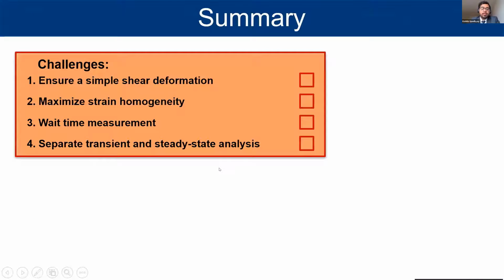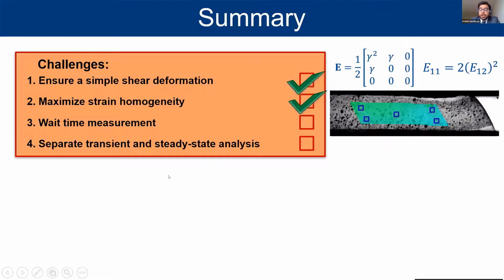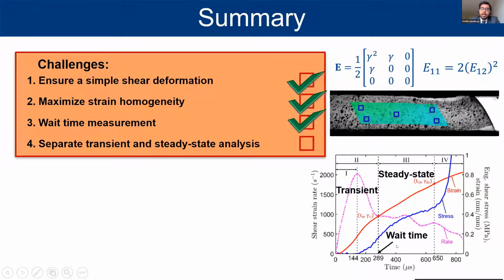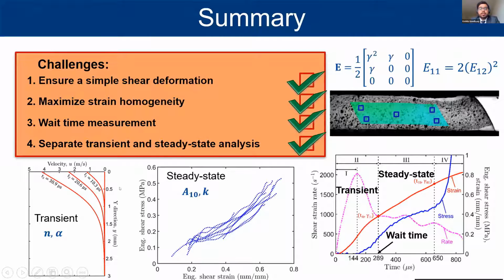So in summary, I have designed a new simple shear experiment in the dynamic regime that not only gives me a correct simple shear deformation with homogeneous strain field, but with the idea of the wait time, I can also analyze the two stages of deformations separately, all with a single experiment without requiring any extensive modifications to the test setup and just using the traditional compression SHPB setup.